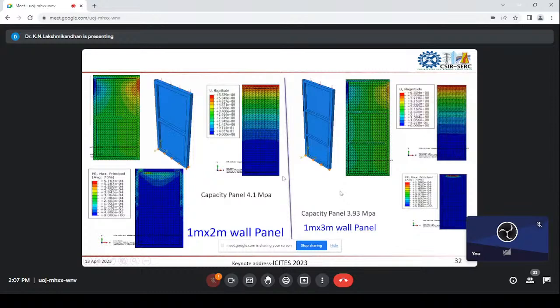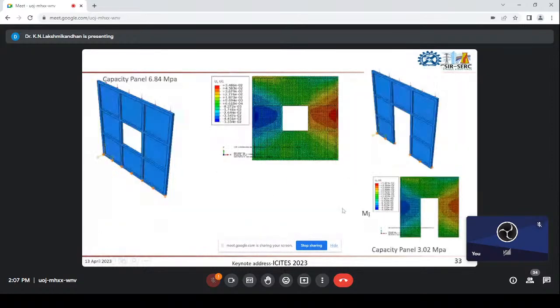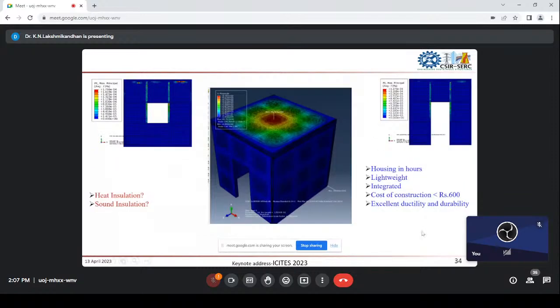We examined this using the finite element software that we have. These models are created using Abaqus, with the concrete damaged plasticity model. We checked different configurations for developing a house, with openings, that is window or door openings, simulated in the software and integrated together. We found that it behaves the same way as conventional structures, with a very low cost as well as dead weight. Because of this reduction in dead weight, it is normally more advantageous during any earthquake or lateral load distributions.